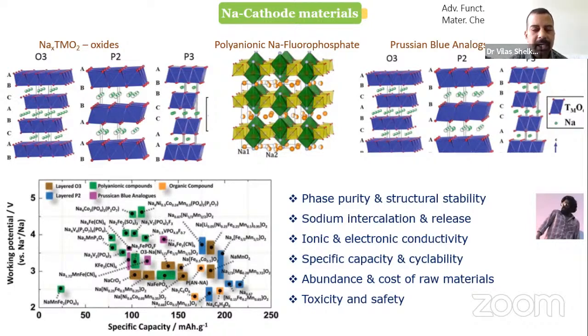Specific capacity, because the entire energy density of the battery depends on the specific capacity of the anode material and the cathode material. So when we invent or try to synthesize a cathode material, you have to always test the specific capacity of the cathode material, the anode material, and then collectively for a full cell combination, you have to measure the energy density of the cell. And cyclability also is important, because of how many times these ions can shuttle between cathode and anode. So how many cycles this battery can be charged or discharged depends entirely on the material used for cathode fabrication or anode fabrication.